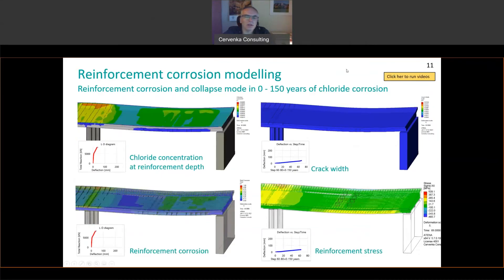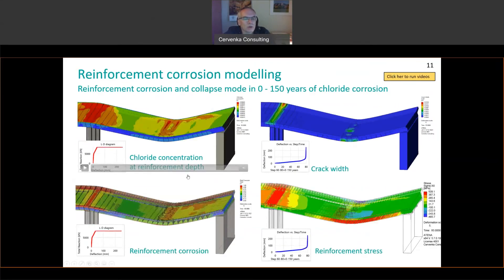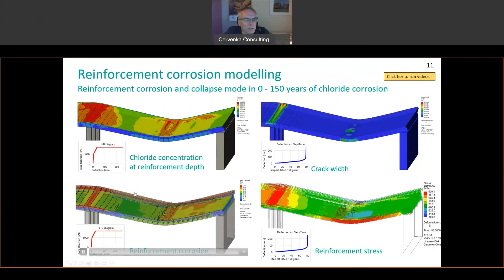Now let's look at some results from this simulation. The top left figure shows the chloride concentration at the depth of the reinforcement. You can see nicely how chloride concentrations at reinforcement depth are affected by the presence of cracks. At the bottom, you see the evolution of reinforcement corrosion — the red area is fully corroded, while the blue color indicates reinforcement without any corrosion. Again, you see mainly the effects of cracks above the support, where corrosion is fastest.